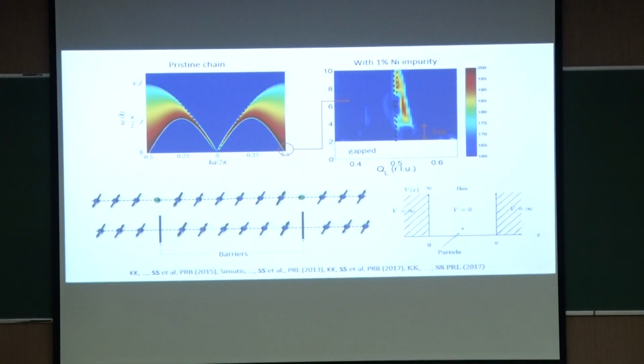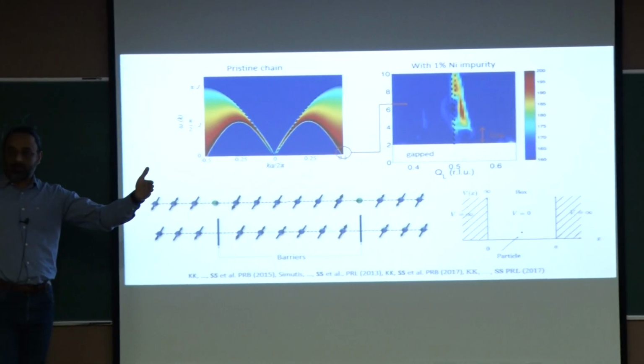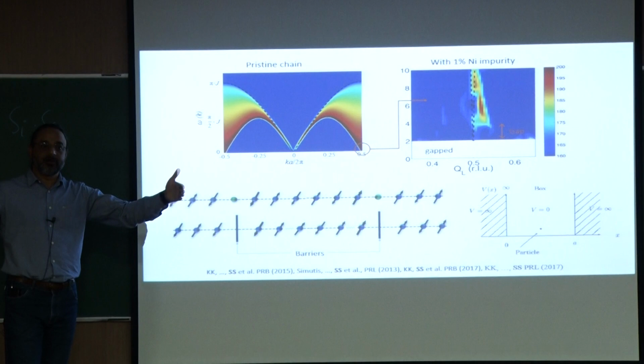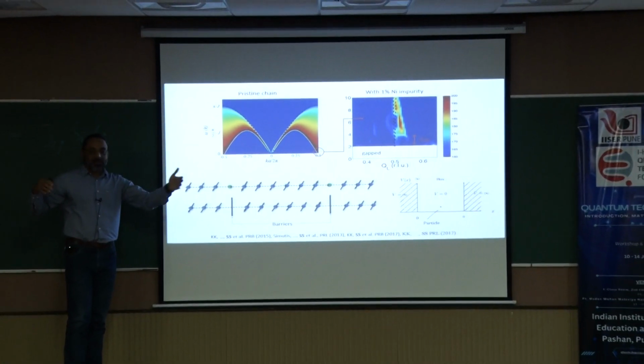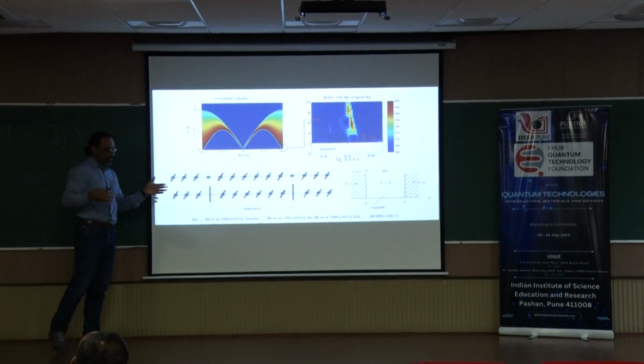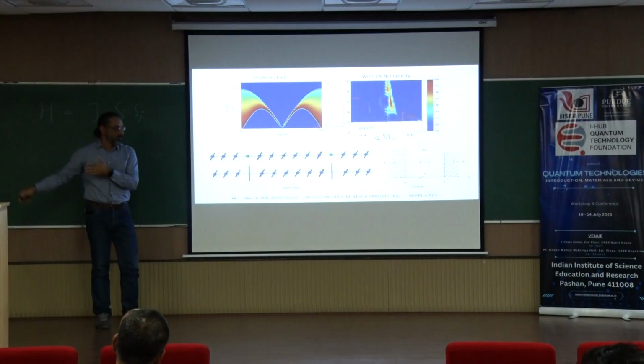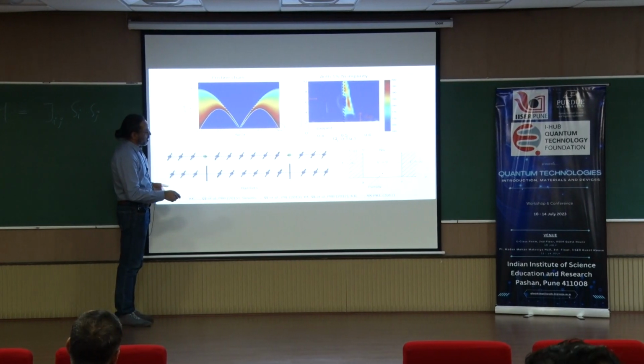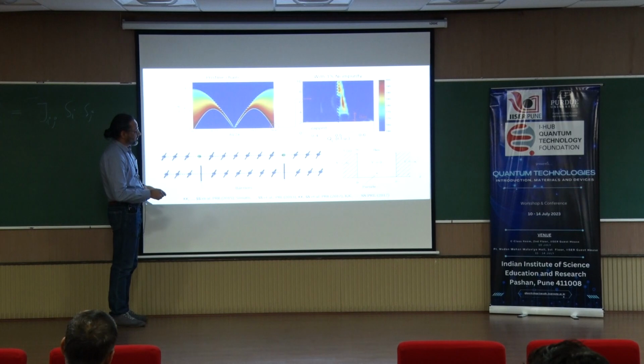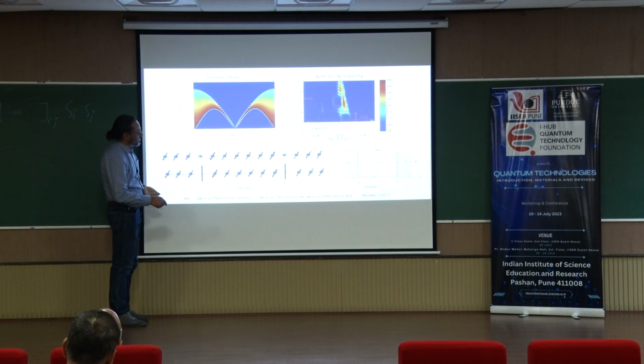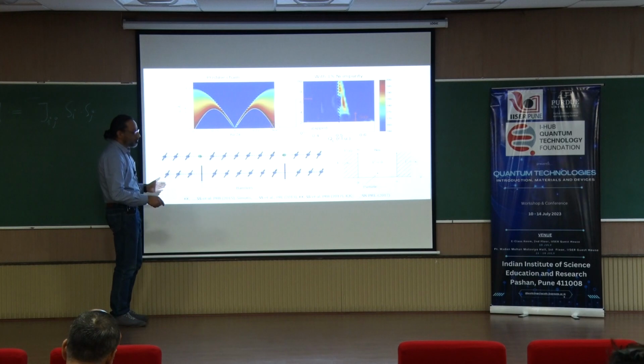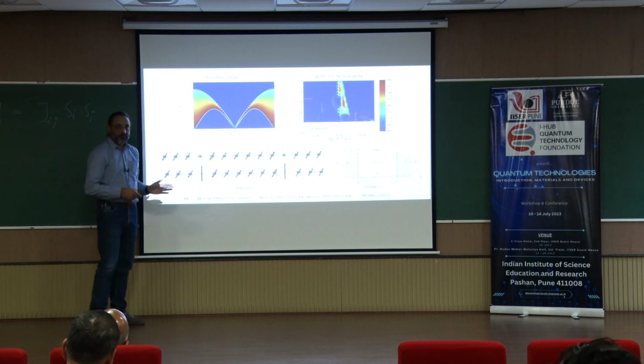Now, if you dope your chain with a very small amount of impurities, you will get finite chain lengths where the chain looks like the pristine chain, and then you have this point, and then you have the next segment, and so on. So the spinons would be created in these sections of the chain, but the spinons are actually confined between these two boundaries. This will act like a boundary. Why? Because as I told you, the translational invariance is lost here. So you have these two boundaries, and the spinons are confined within them.